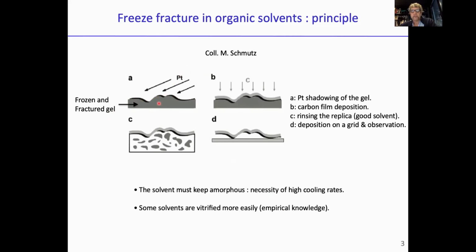Then the gel is kept at low temperature and shadowed by nanoparticles of platinum at an oblique angle to have this impression here, so that we have areas that are shadowed and others not. And then carbon is evaporated on the sample, and then the gel is rinsed. So finally, what you observe, there's no more gel, it's just a replica, and it's collected on the grid for observation.